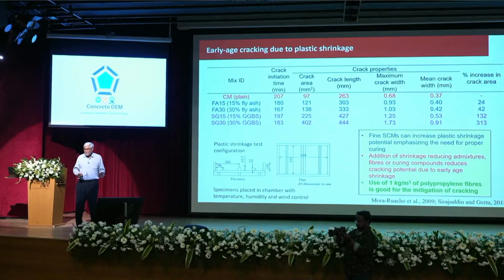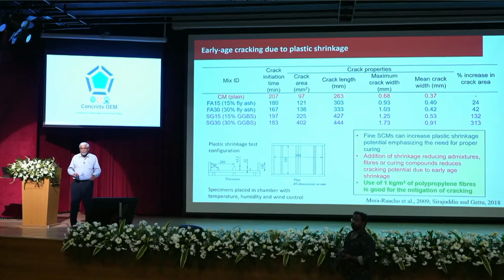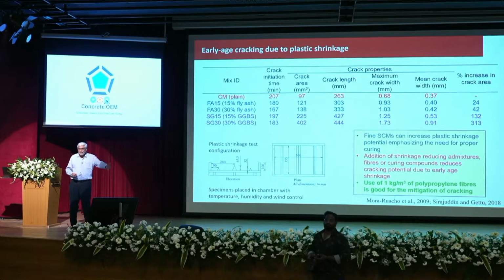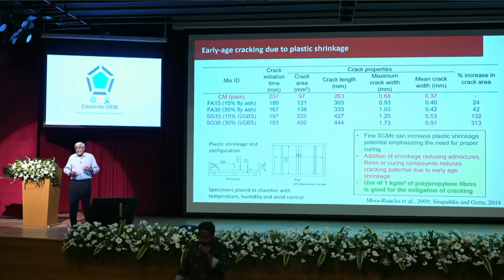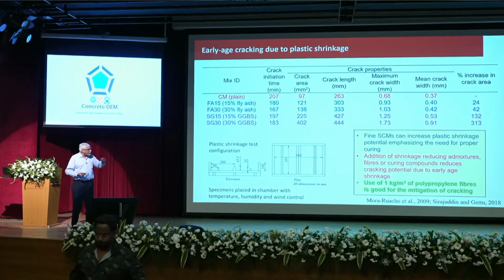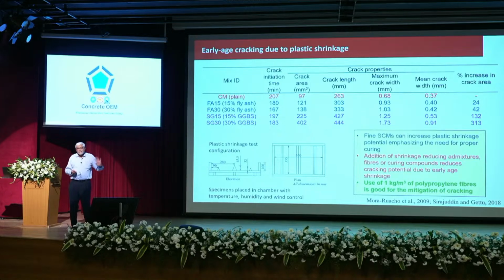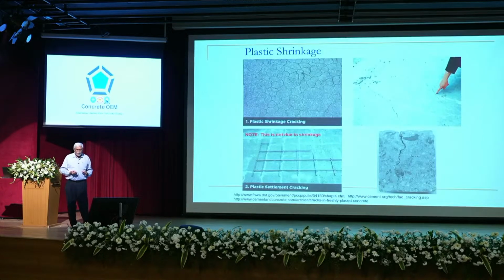You cannot push your thumb inside. And this is very, very important for concretes which have fly ash, which have slag, and so on. If you cannot cure, then put a little bit of polypropylene fibers. Just 1 kilogram of short polypropylene fibers will help probably eliminate the plastic shrinkage cracking. Very simple cure. We don't have to panic. And this can be done and has been shown to work. Otherwise, you will have cracks like this. Pattern type cracking, random cracking, this is usually plastic shrinkage cracking. Okay?